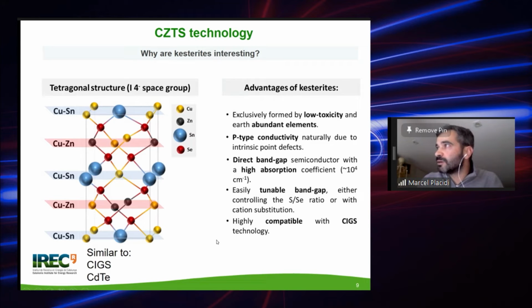Okay, other advantages of kesterite are that they are formed from low toxic and earth abundant elements. We have said that. They also naturally have a p-type conductivity. There are intrinsic defects that render this material naturally p-type. The band gap is direct with a very high absorption coefficient, and this is perfect for solar cells. And there is also one criterion which is very interesting, and it is the tunability of the band gap. The band gap can be tuned depending on the composition, mainly on the anionic composition, but also on the cationic composition. We can replace, for example, copper with other elements, and the band gap can be tuned.